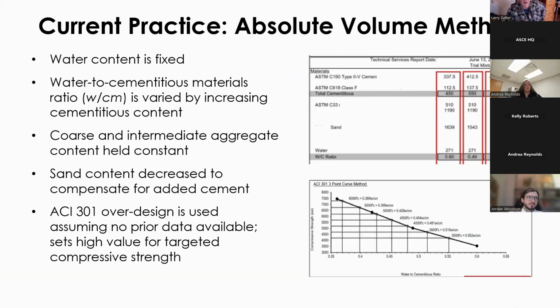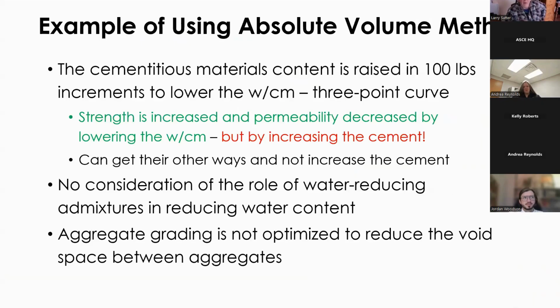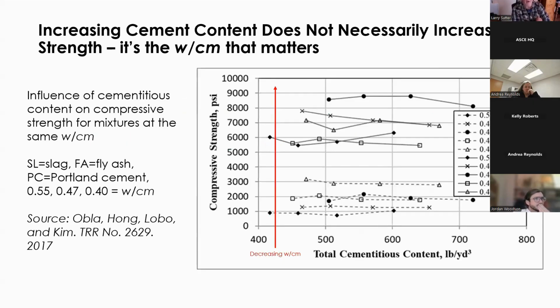Next slide. And so what we end up with is we're increasing this cement content by 100 pounds to adjust the water to cement ratio. And of course, strength is increased as we decrease the water to cement ratio, and permeability is decreased. But we're doing it by increasing the cement. We're not acknowledging any of the current things we have at our disposal, such as water reducers and optimizing the aggregate gradation.